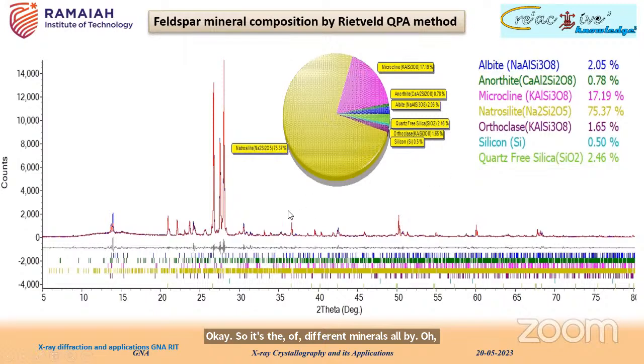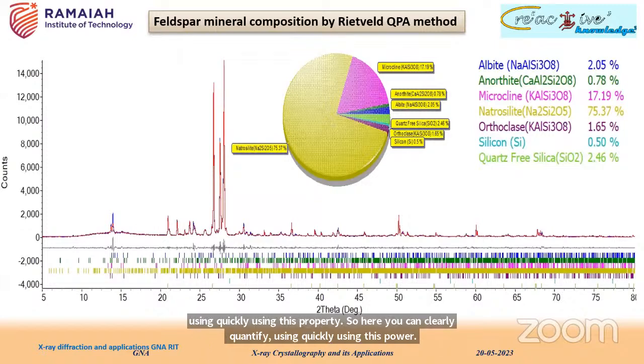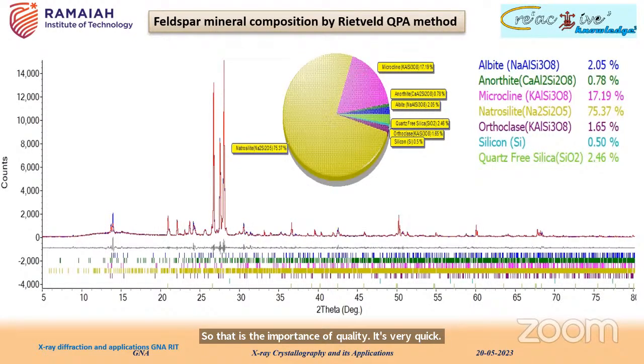And so you can actually quantify all of them. The analysis gives you what percentage of each mineral is present in the mixture, in this raw material. So here nearly 8 phases are there. No, 7 phases are there. Some of them are high and some of them are low. So here you can clearly quantify using this powder diffraction technique. That is the importance of the powder technique. It is very quick and versatile and gives results very quickly.